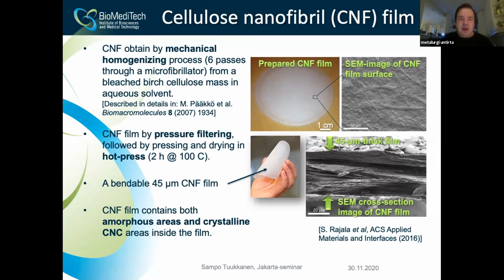And then after this, when we got the nanocellulose out from this mass, we used pressure filtering to dry the mass into a film and remove the water. Then we used a hot press to compress it to make the film stiffer, get extra mechanical properties, and make it more dense. What we ended up with was an about 45 micrometer thick CNF film.